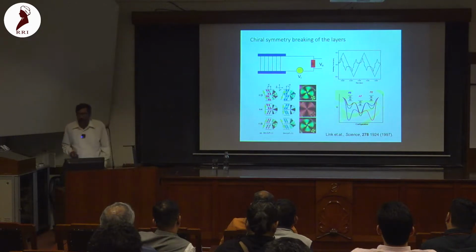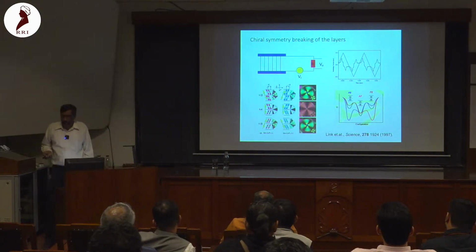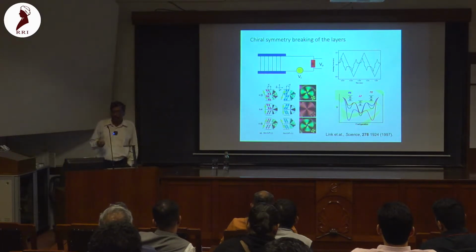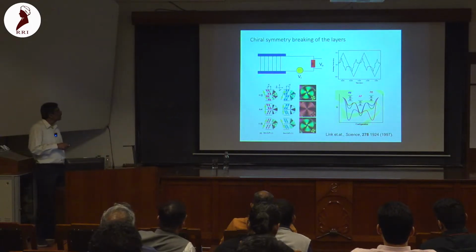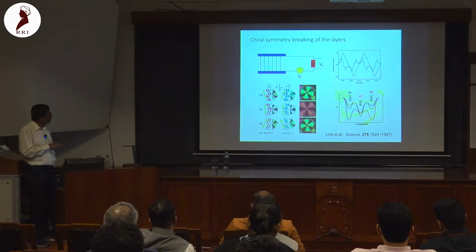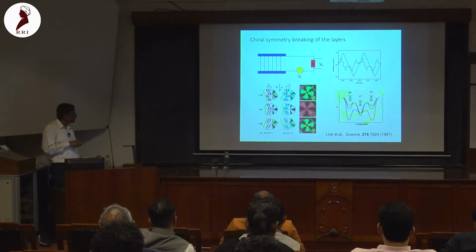Now you will ask, how do you know whether there is polarization in the medium? And if there is polarization in the medium, whether it is antiferroelectric or ferroelectric. One technique they have used is they put the sample between two glass plates, and between these two glass plates, the layers are like this, vertical. So they form some kind of texture like this. The layers are now circular layers going down. So the layers are perpendicular to the plate, but they have a circular structure.